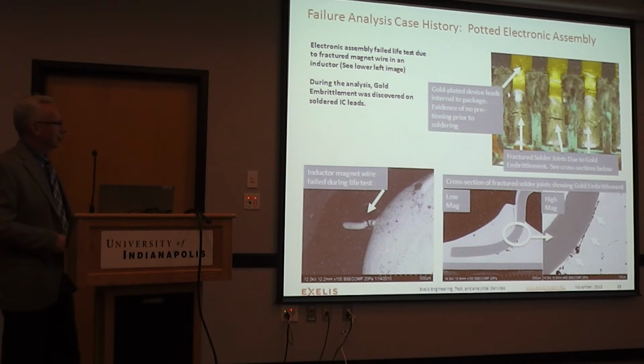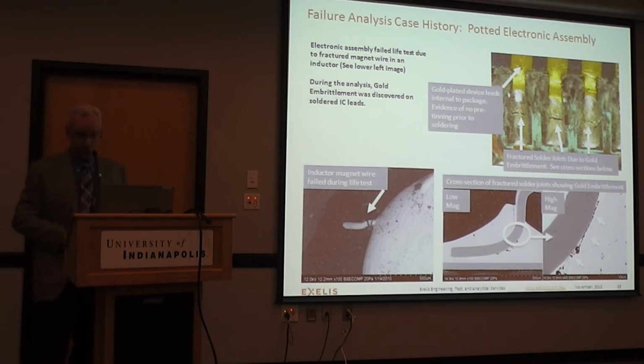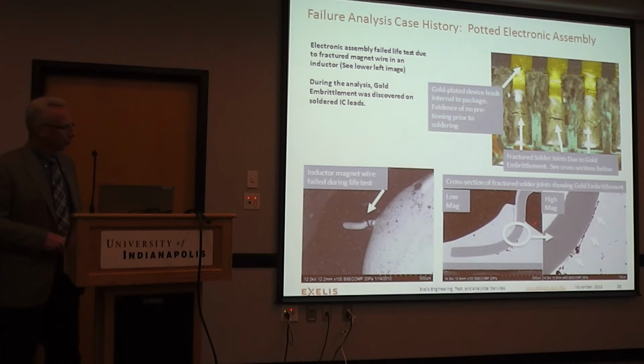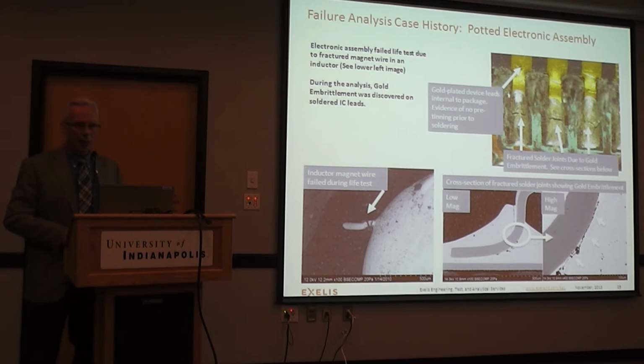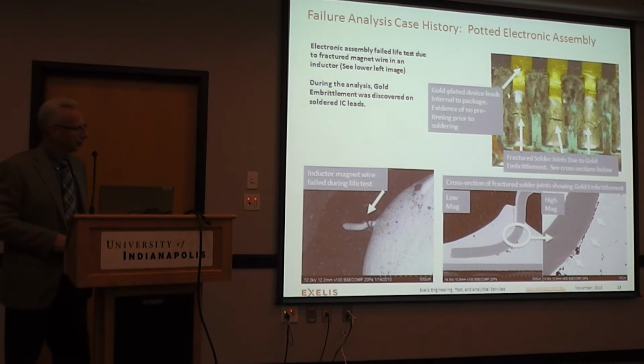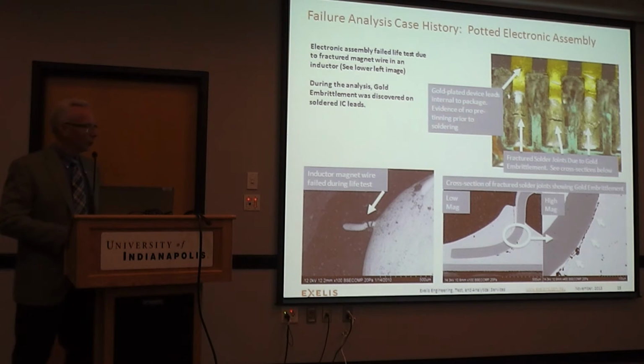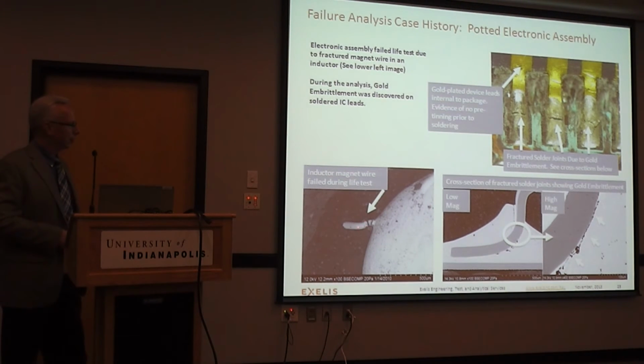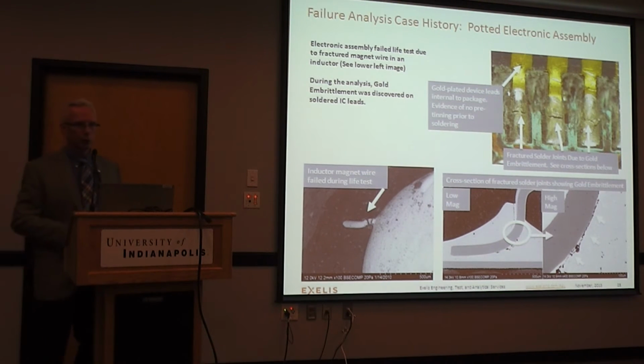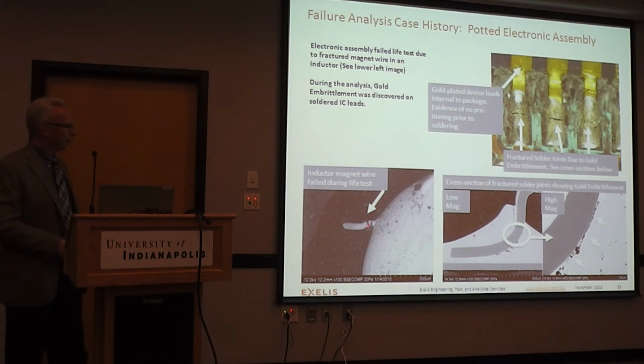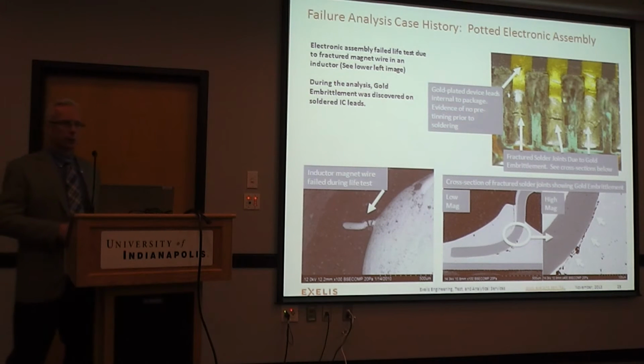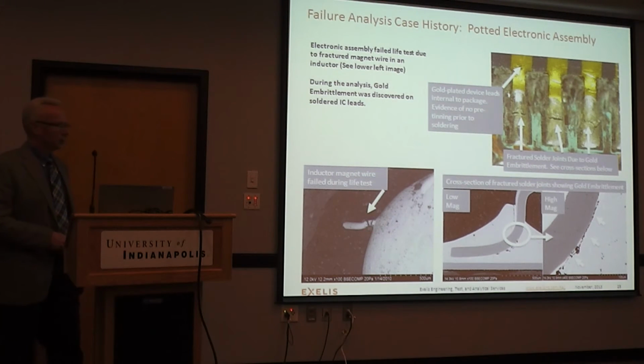And of course, I have to give you a bonus. So the bonus failure mechanism was that there was an inductor magnet wire that broke, and that was actually the cause of failure in this potted device. So the gold embrittlement was kind of a latent failure waiting to happen, but there was still electrical continuity in all these peaks and valleys of this fracture surface within the gold embrittled joint. So this magnet wire failed during test, most likely due to lack of strain relief within that assembly. You can see it fractured as it enters into a solder joint, probably at the point of greatest stress concentration. So just as we would expect. And if they would have put more of a strain relief in that magnet wire as it approached, most likely it would have survived.